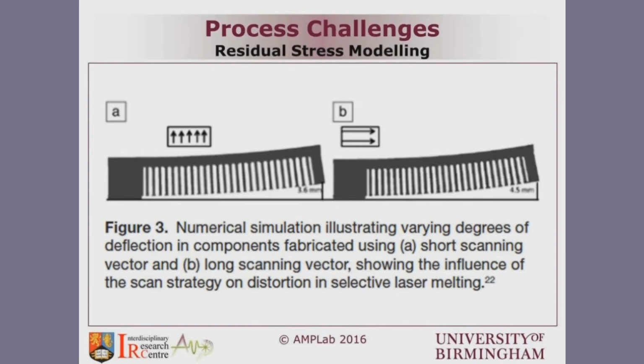The short scanning vectors gave slightly lower distortion, which in our case explains that it has lower stresses inside, lower tensile stresses in that component. The component was validated by building the actual part, then using wire EDM to cut the teeth of the comb, except for the left-hand side end.